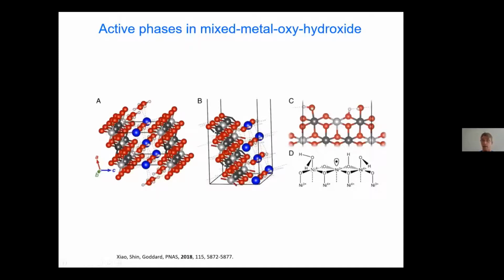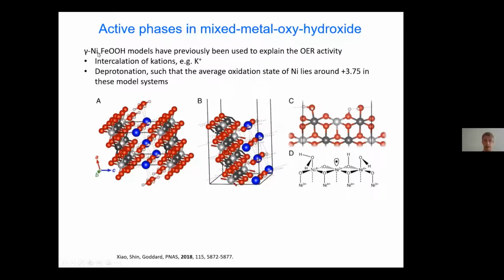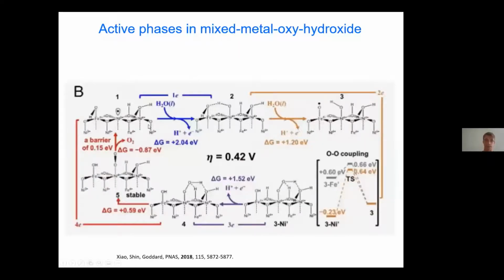So to explain now these trimetallic metal oxyhydroxides, I took a look in literature and found a study on gamma nickel iron OOH models. So gamma means we have intercalation of potassium and water within sheets of metal oxyhydroxides. And then one of the edge atoms within this system is the active site. So these are calculated reaction pathways from literature where they found a quite low overpotential for iron nickel oxyhydroxide systems, but not so low as observed experimentally.